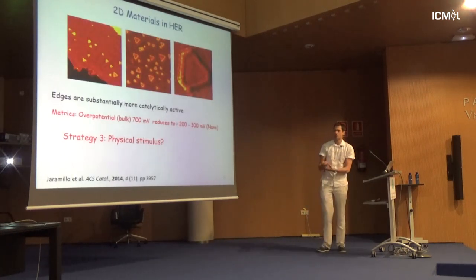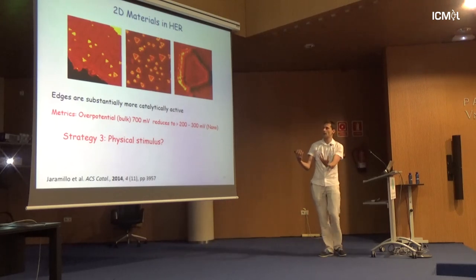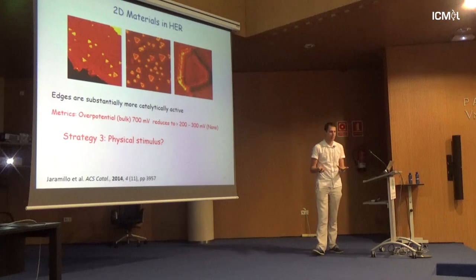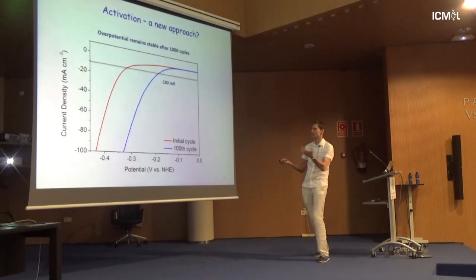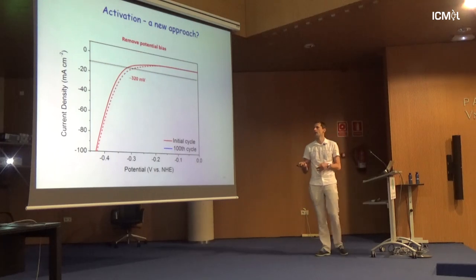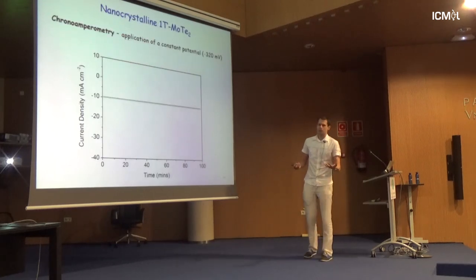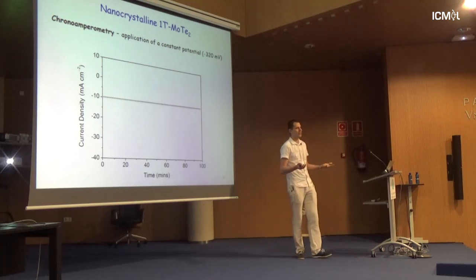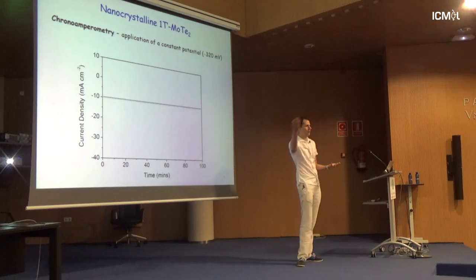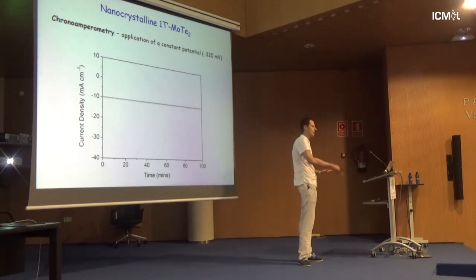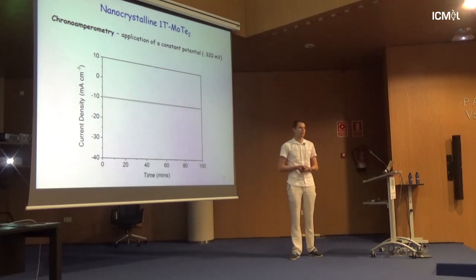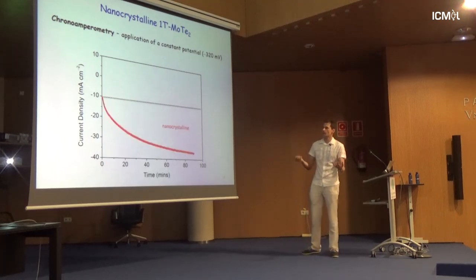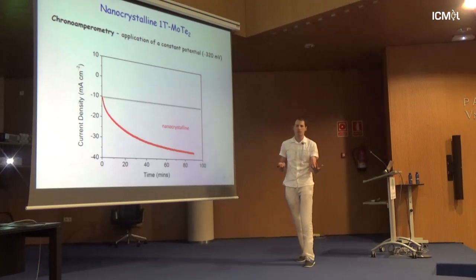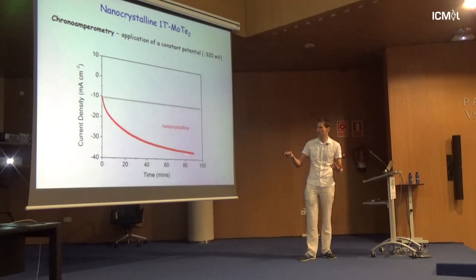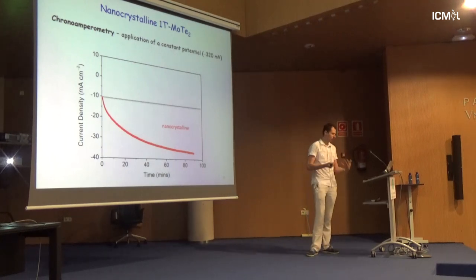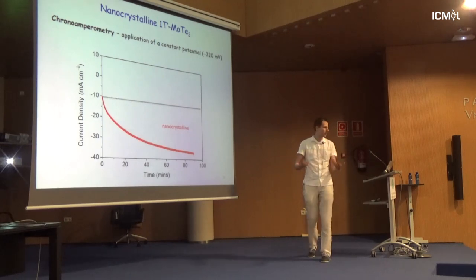So, which brought us to this third strategy. How we can play with 2D materials is with physical stimulus. And so just again this graph, you turn it on, turn it off. And very important, there's a lot of effects. Cyclic voltammetry is not steady state, especially reducing, there's a lot of effects happening. And it's very important to measure it in a steady state. For example, you apply this stable potential, and then you see how your current density changes. And the current density genuinely changes, so it improves, so the material improves.